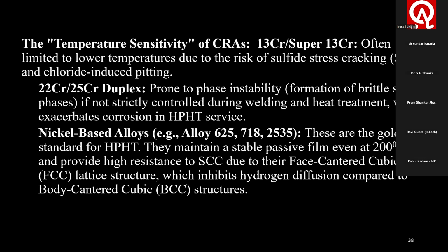Furthermore, 22 chromium to 25 chromium duplex is prone to phase instability. That means formation of brittle sigma phases if not strictly controlled during the welding and heat treatment, which exacerbate corrosion in HPHT services. If you talk about nickel-based alloys, say 625, 718 and 2535, these are the gold standard for HPHT. They maintain a stable passive film even at 200 degrees centigrade plus and provide higher resistance to stress corrosion cracking due to their face-centered cubic lattice structures, which inhibits hydrogen diffusion compared to body-centered cubic BCC structure.